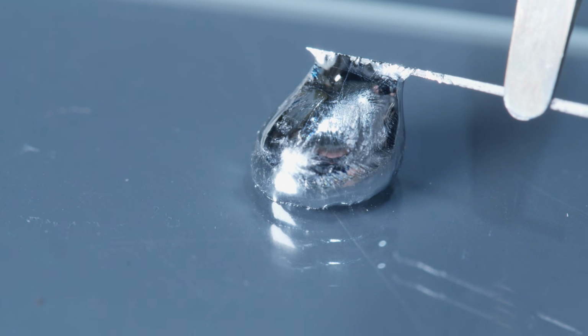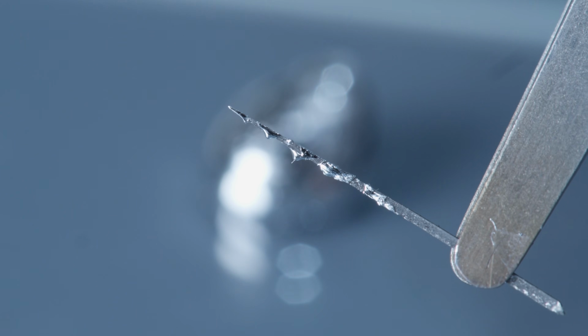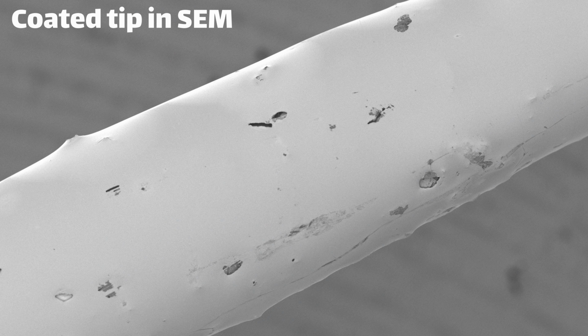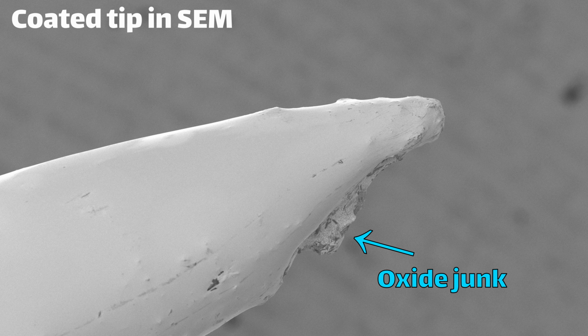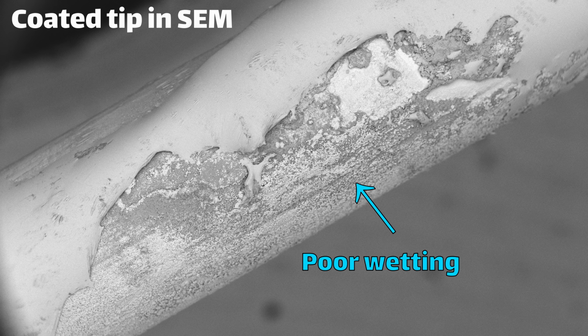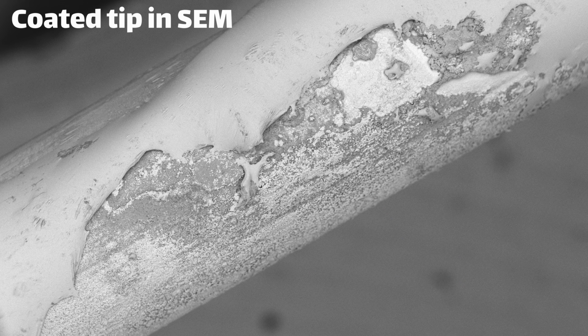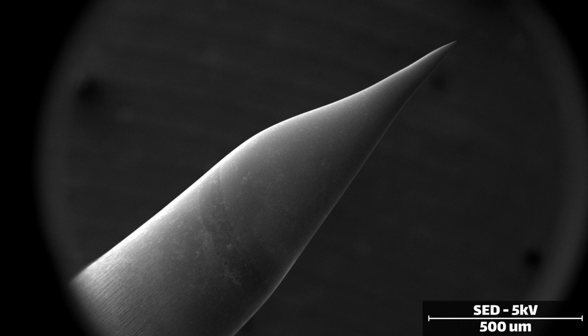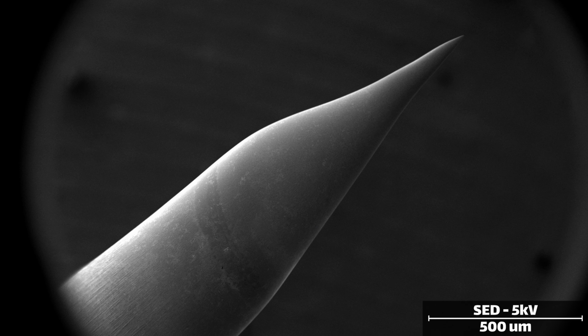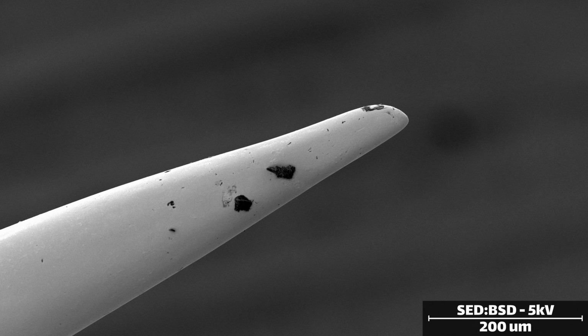Gallium is sitting on these tips, but they aren't really wetting out correctly when you look closely. It's full of holes and there's lots of oxide junk kind of sitting around. The tests that worked may have just been a lucky fluke. Another issue is the surface roughness of these tips. The electrochemical process makes a very sharp tip, but it also makes a very smooth tip.